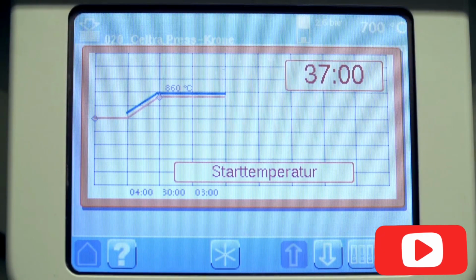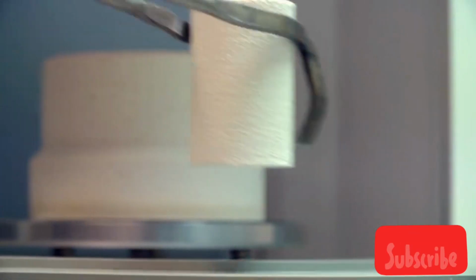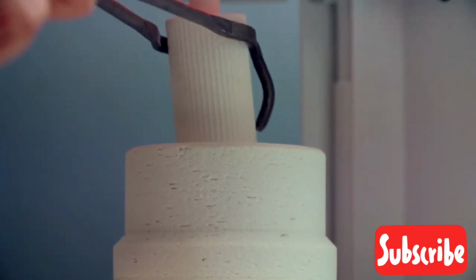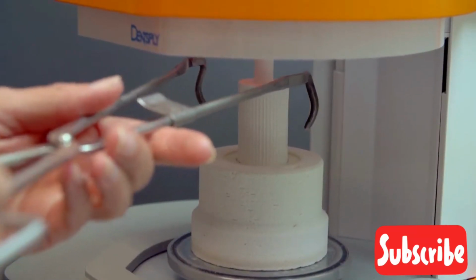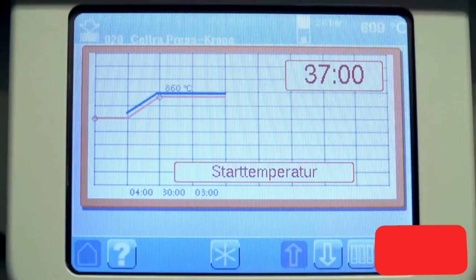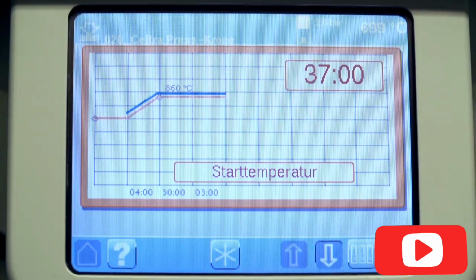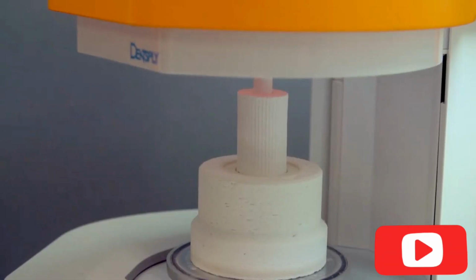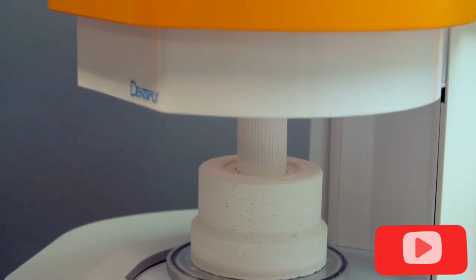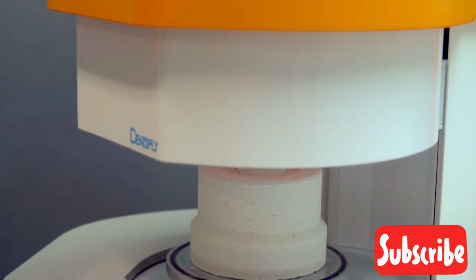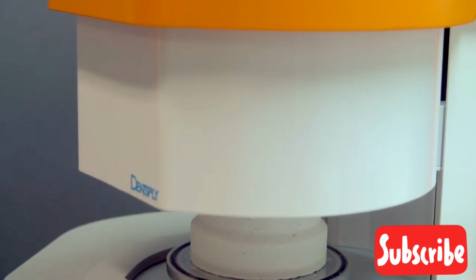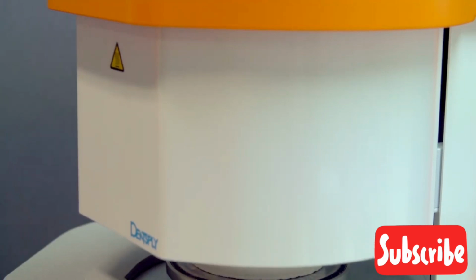Once the pressing furnace has reached the starting temperature of 700 degrees Celsius, we place the entire assembly in the furnace and start the program. On completion of the pressing procedure, the muffle is removed, placed on a heat-proof surface, and allowed to cool to room temperature.